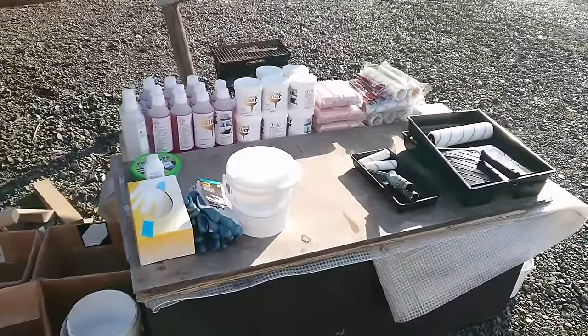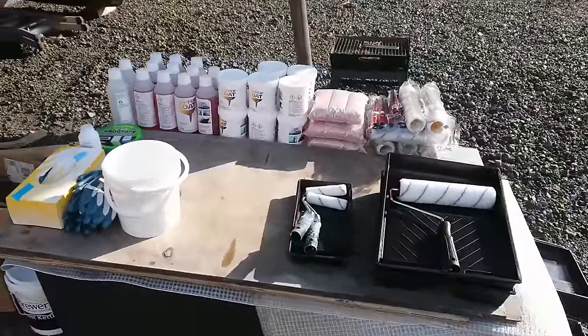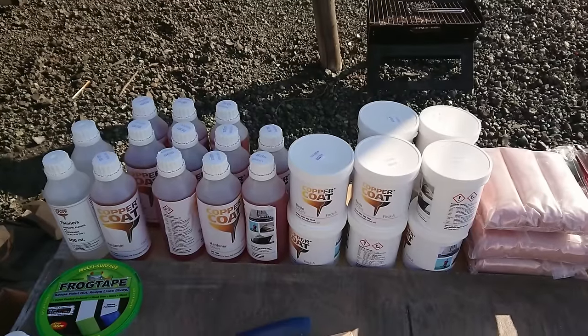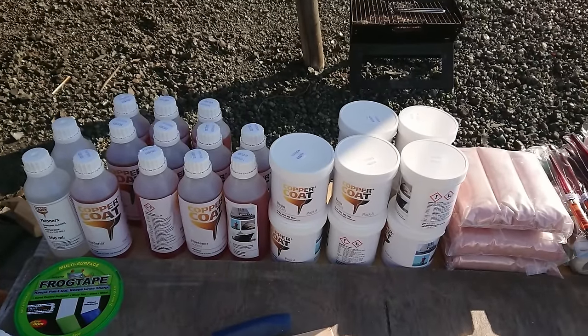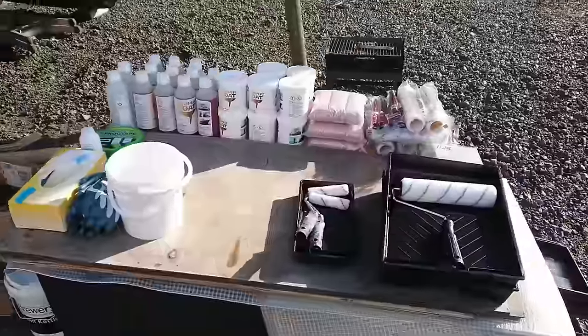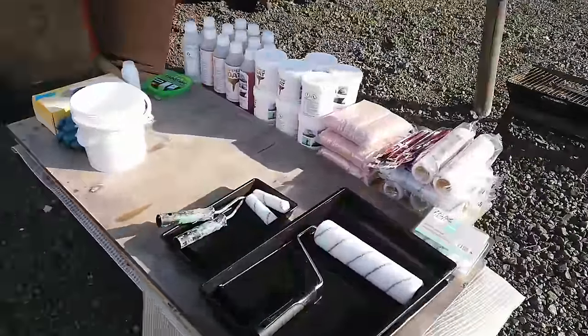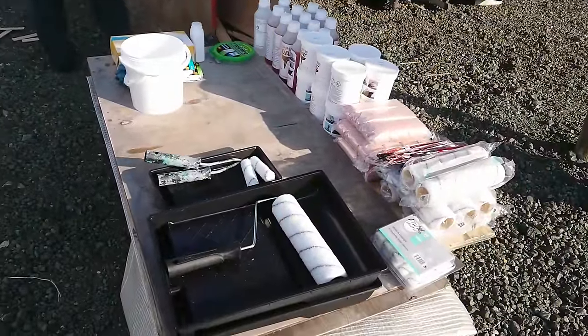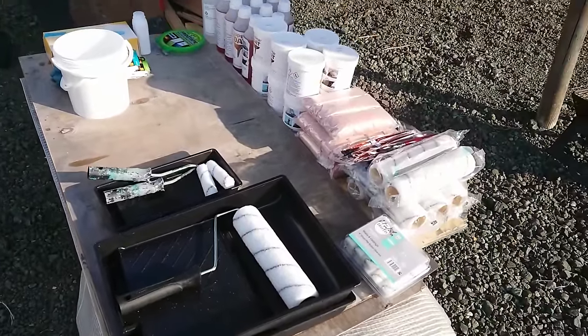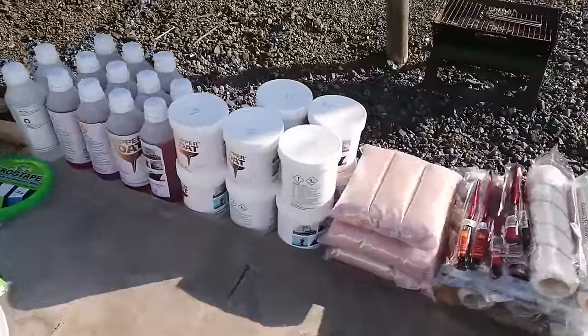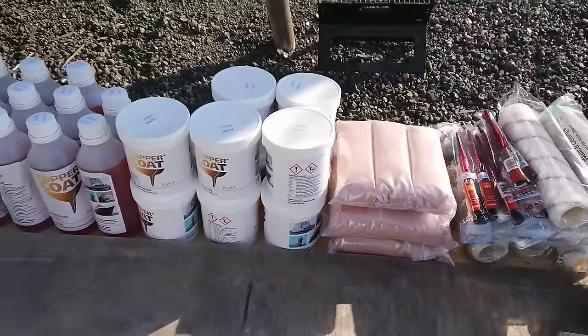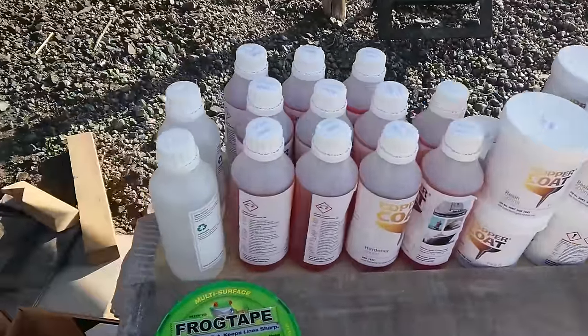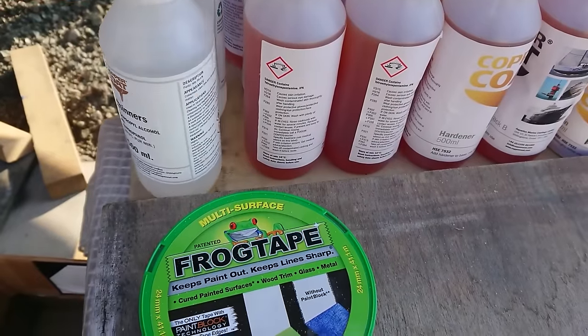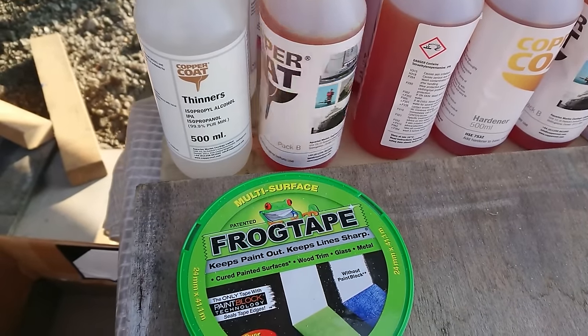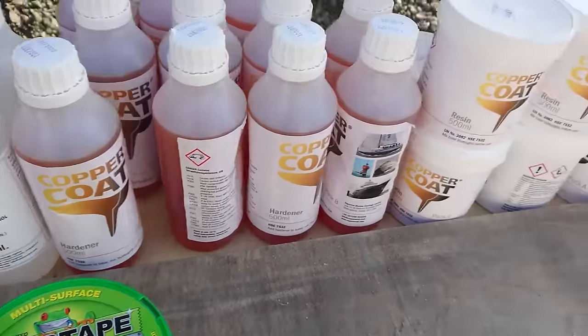This is what 1,100 pounds worth of copper coat looks like. We'd calculated for the 5 coats we planned on applying, we needed 11 packs to cover the area under the waterline. Each pack consists of a 500 milliliter tub of resin, a 500 milliliter bottle of hardener, and a 2 kilo bag of very fine copper powder. We also got a couple of bottles of isopropyl alcohol that's used as a thinners. We laid everything out we were going to need ready on the table.